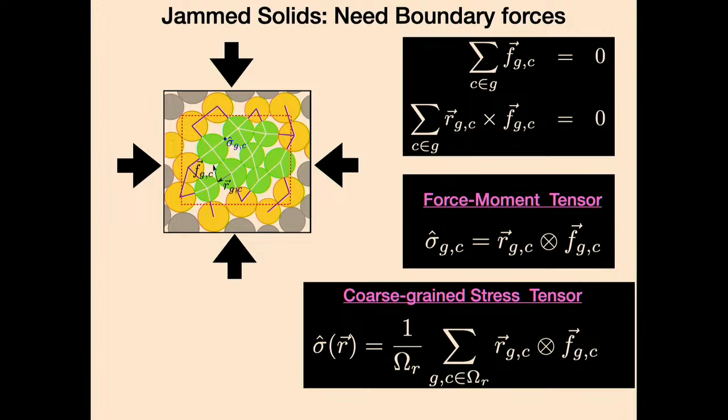This system now satisfies constraints, which is force and torque balance, at every point. So think of this as analogous to satisfying divergence of E equal to 0 in my previous system. This is just divergence of this coarse grain, which will give me divergence of sigma equal to 0. This will give me sigma is symmetric, but this is another conservation law.